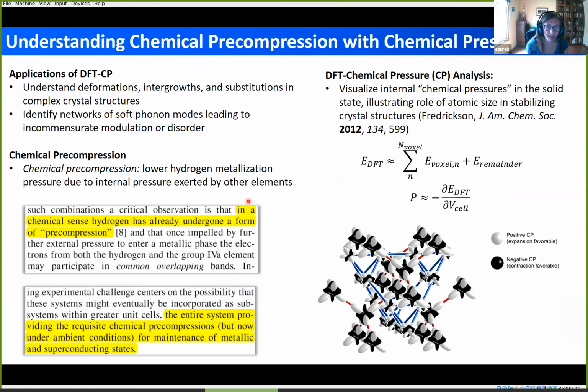To do that, we decided to use the chemical DFT chemical pressure analysis to look at the internal pressures within these systems. This analysis was made by the Danny Fredrickson group, and until now it has been used primarily to understand deformations, intergrowths, and substitutions in complex crystal structures, and also to identify soft phonon modes that could give rise to some sort of incommensurate modulation.